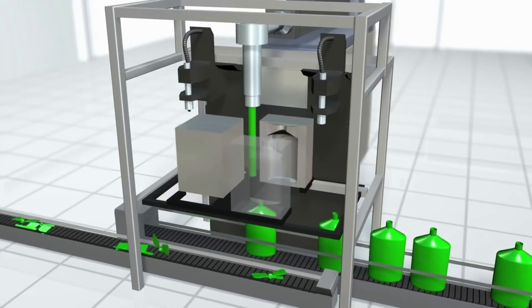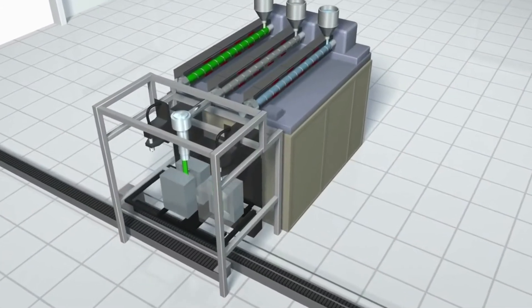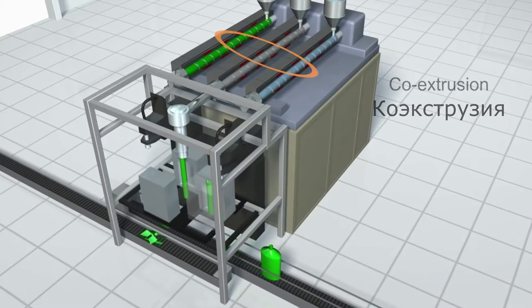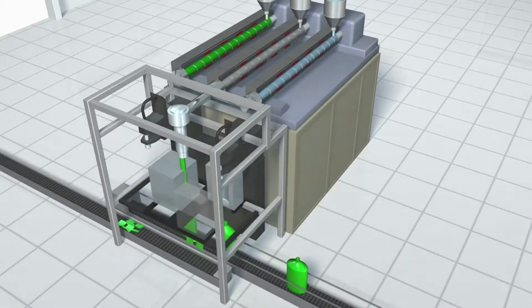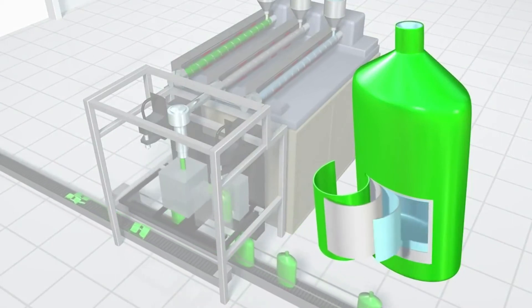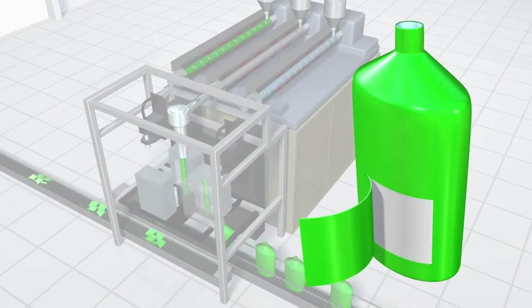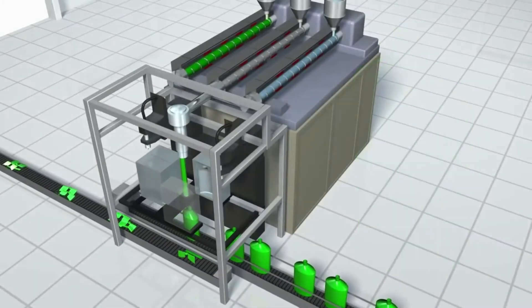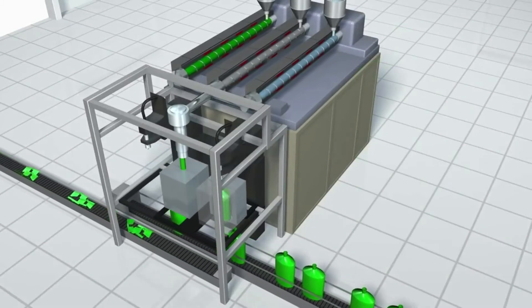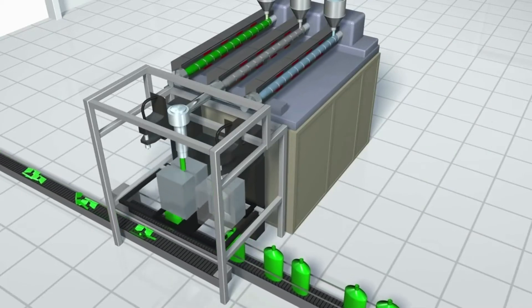The same blow molding process can also utilize multiple extruders for what is called co-extrusion. Co-extrusion is used to create bottles made up of multiple layers, and each layer possesses special characteristics like suitability for food contact, outside color for brand awareness, ultraviolet light protection for long shelf life, a layer of regrind for economical reuse of scrap, and barrier and adhesive layers to separate and bond the layers for a tough, cohesive bottle.